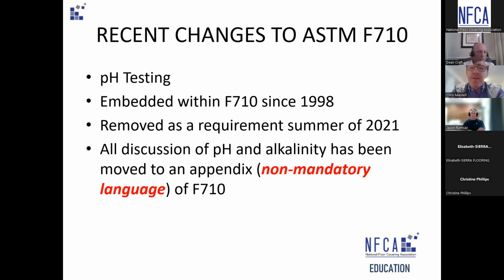Considering the way concrete's going these days, just getting more and more alkaline in nature, that's a good point, because with the 1L cement and the increased amount of limestone and calcium carbonate, if it goes into solution, it will be a higher pH. It's good for concrete, by the way, because alkalinity helps protect embedded steel and rebar and structural steel. But it is curious if it will swing back the other way.